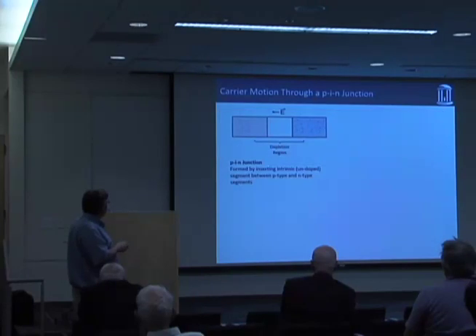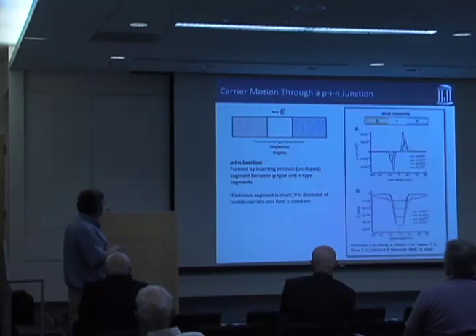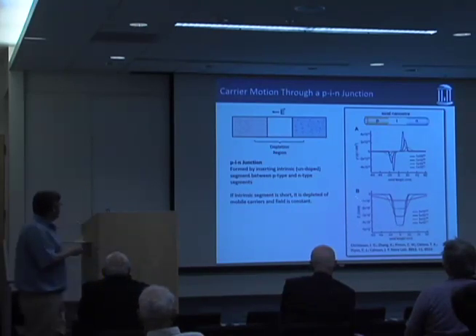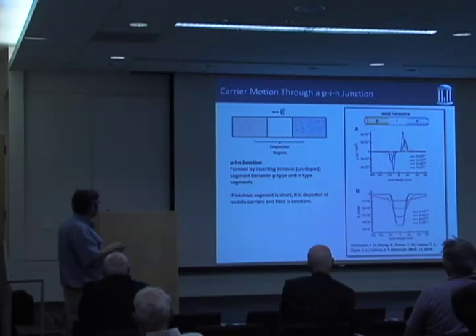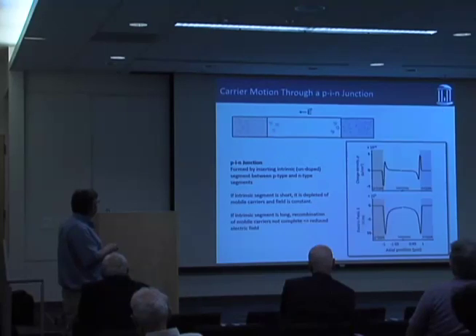And so Jim's group has made what are called PIN junctions, where you have an undoped layer in between the P-type and the N-type material. And all this really does is extend the depletion region, makes it a little bit bigger. And his group has done simulations on these things and modeled charge densities and fields that you get in these junctions. But everything that they had grown had an intrinsic layer of like 50 nanometers or something like that. And what we really wanted was something a little bit different. So they made us one where this intrinsic region was much larger. It's like 2 microns long.